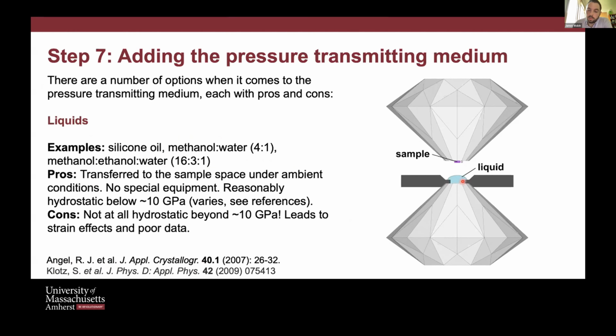You add a sample drop to the gasket side, which has nothing in, and then you bring the other side into it. And at some point it's going to break the surface tension of that bubble, and hopefully nothing moves. Sometimes it does. And then you've trapped in that liquid with the gasket. If you put the sample in the gasket, not only is that a bit more tricky to do because the gasket's in the way while you're actually loading it, I tend to find that when you add the droplet, that kind of washes the sample away. So try it this way. I've had most success with this method.